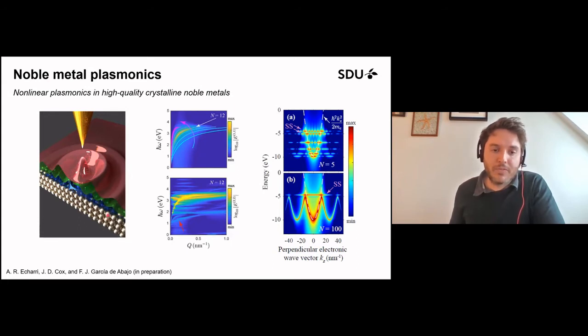And again, what we find is that you can also tune the nonlinear response by changing the thickness of the material in terms of the number of atomic planes you have. And in going to very, very thin materials, you win in a way because you take advantage of the quantum finite size effects that you get in the electronic structure. So you can see that the electronic density of states here is very different for a small film with only 5 monolayers compared to a thick film with 100 monolayers. So this is meant to motivate further explorations in that area.